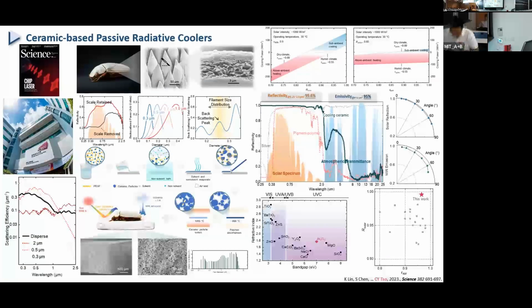As we know, if we put a polymer outdoors for about one year, it has strong degradation. The polymer will first become yellow and then become brittle, so polymer material is difficult to sustain in an outdoor environment. If we use metal oxide, which is an inorganic material, we can typically solve the UV degradation problem. That's why we chose aluminum oxide, and we optimized the pore distribution and the size of the pores. We can achieve the highest 99.6% solar reflectivity, with also very high emissivity in the 8 to 30 micron range, about 95%.